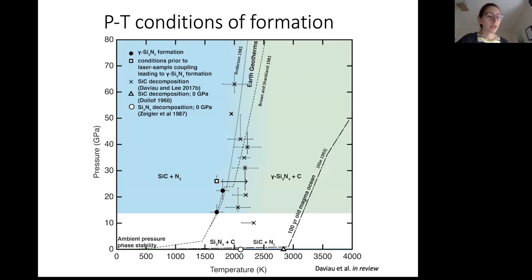Right, so if we put together a phase diagram of this silicon carbon nitrogen system that we're looking at, these circular data points and then this square correspond to where we see silicon nitride formation. So again, it's fairly consistent with the previous data shown in X's here, where we saw the beginning of decomposition.